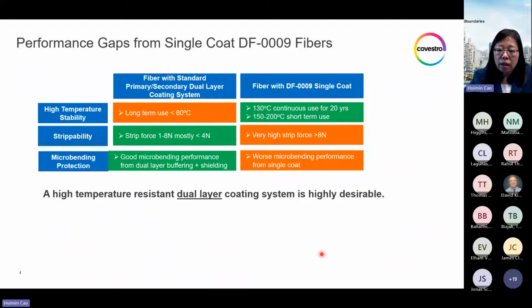For gap analysis, if you compare the single coat DF-0009 with a standard primary and secondary dual layer coating system, DF-0009 for sure has much better thermal stability at high temperature, but there are intrinsic performance gaps compared to a dual layer coating system, such as the strip force being much higher. This is because the 60 micron single coat requires much higher force to buckle and break than stripping a dual layer coating system, which has a 30 micron much softer primary coating.